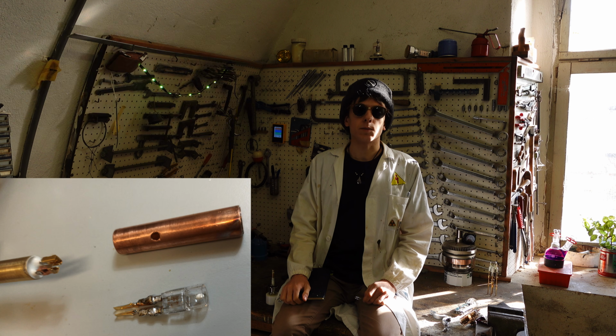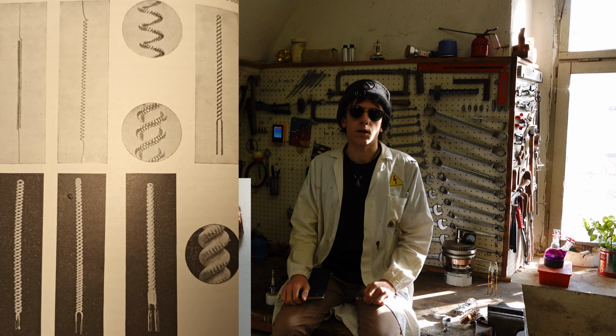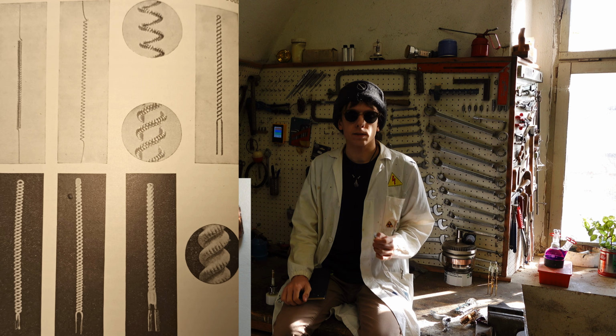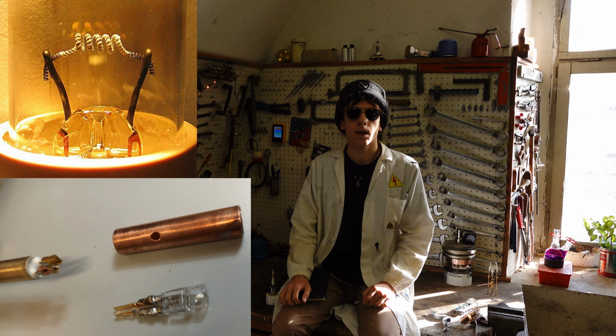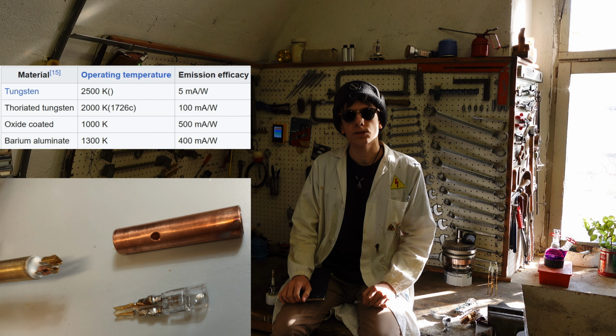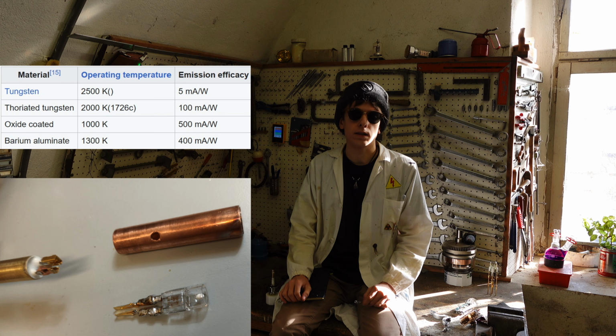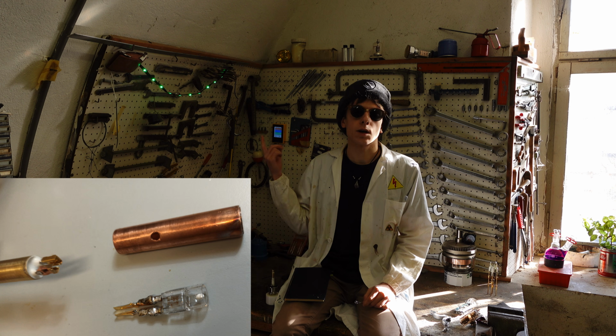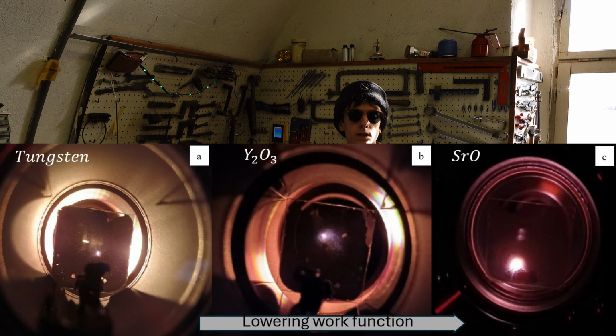This type of cathode employs a thin layer of metal oxide covering the filament to lower its work function, achieving a higher emission at a lower temperature, increasing efficiency and lowering noise. I have been successful in making it work, and here you can see some comparison between the emission current of some of the cathodes I tested.